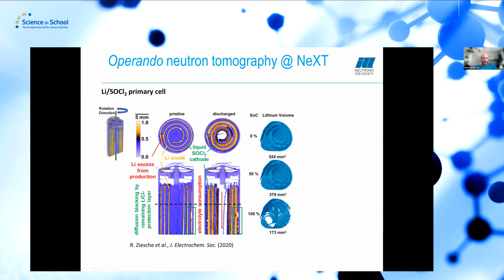If we go through here, the first stage and the last stage are the reconstructed slices that I've shown in the movie. So it's not a superimposed image; it's a reconstructed slice. Temporal resolution is something like half an hour in this case, for rather slow discharging of these cells. And so what you can see is how the lithium metal here, which is a spirally wound bobbin type structure, gets discharged and gets to the thionyl chloride cathode material. So we see here in 3D that the anode dissolves, and in the end you get even bits that are not connected anymore to the main anode material, so to the outer pole.